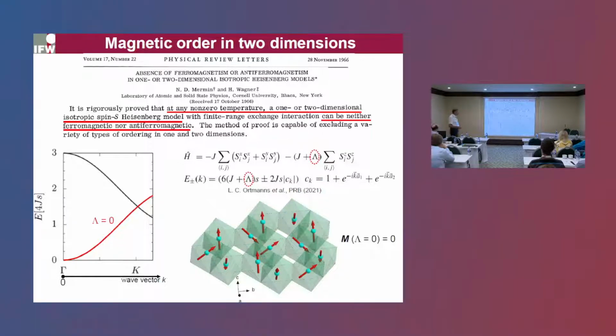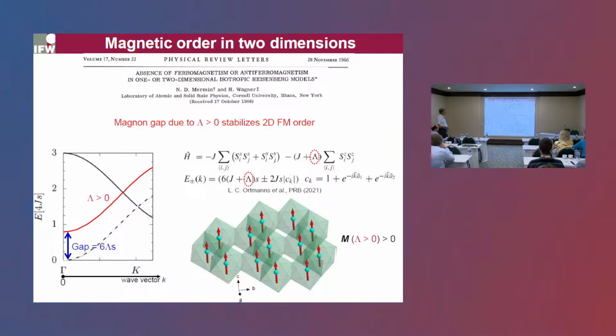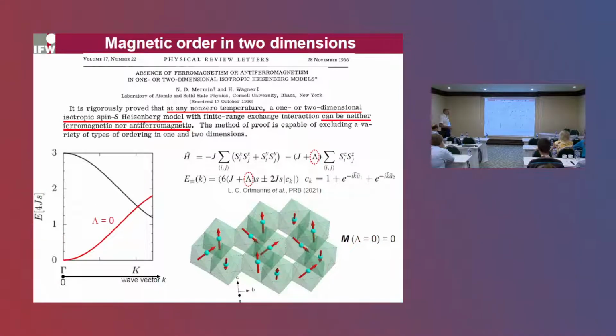The situation may change drastically if one introduces anisotropy. This anisotropy is this parameter lambda. In this case, the energy spectrum acquires a gap which is proportional to lambda. That means if one switches on a positive anisotropy, one can stabilize a two-dimensional ferromagnetic order in the system, because one opens a gap in the excitation spectrum which is proportional to this anisotropy. If the gap is open, then one has full order of the spins in two dimensions. If one closes this gap, the order is destroyed.